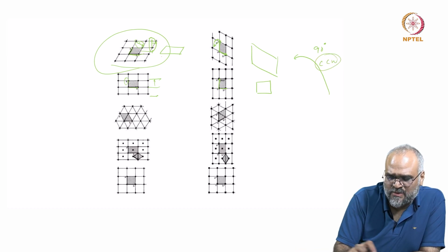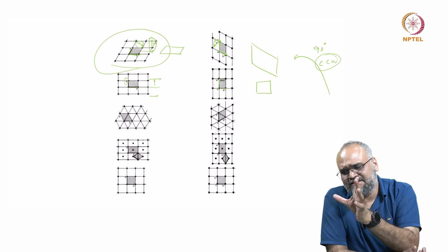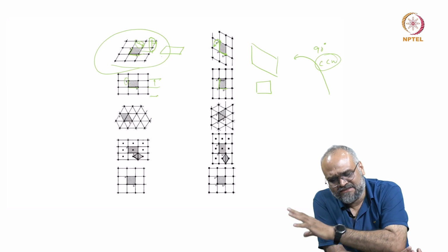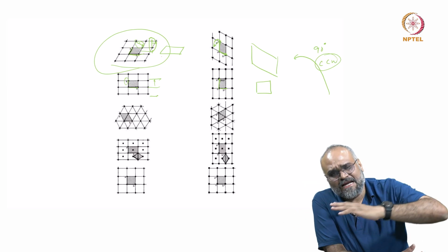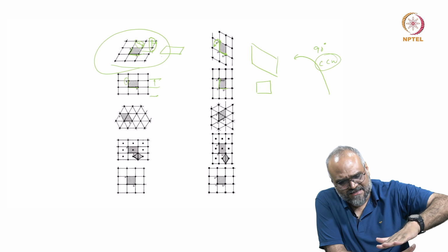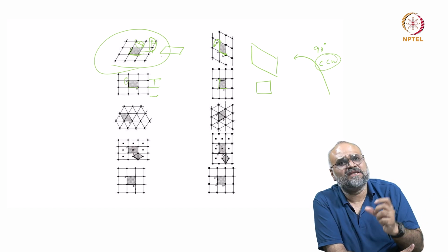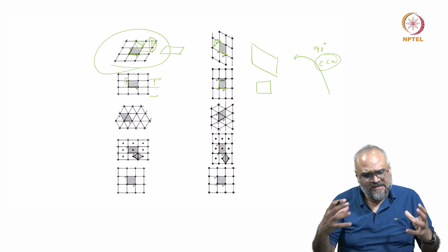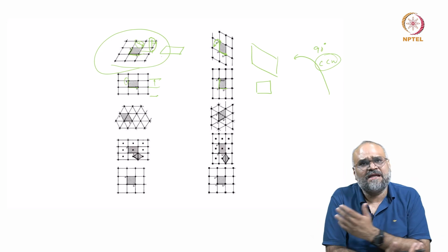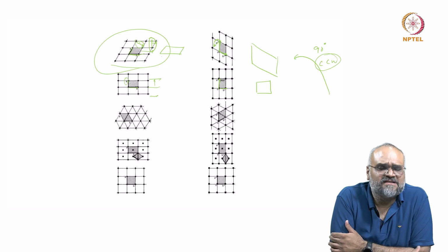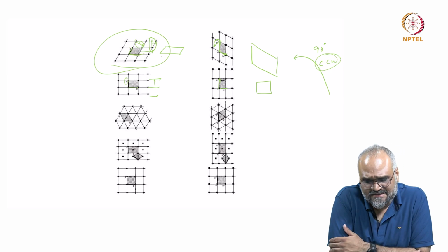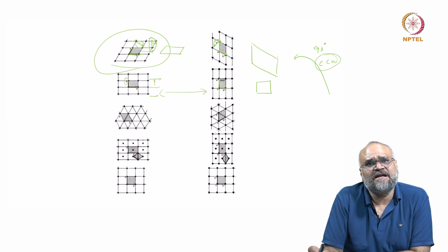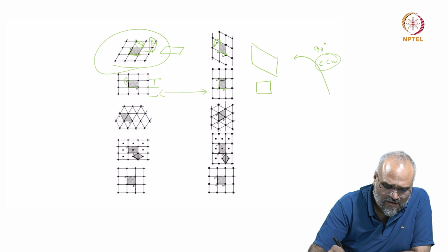So, this is something which you will see in a projection and a Fourier transform that you take in a high resolution TEM image as well. And also when I look at the real space versus reciprocal space relation within a TEM, I usually end up seeing this sort of a 90-degree rotation. That is because the diffraction pattern I obtain in an electron microscope is actually a projection of the reciprocal lattice, and this idea of reciprocal lattice is obtained by constructing a lattice along the plane normals.